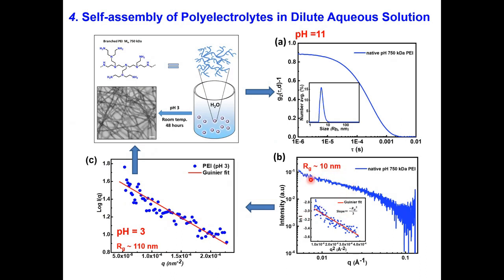And if you remember, I have pulled out this radius of gyration using Guinier analysis. That is, I take a certain region of this particular scattering curve and fit it to this equation, find out the slope and get the value of Rg. So the Rg gives me a value of 10 nanometers. This is for this particular chain only. But if I bring this system to pH 3, now you start seeing these fibrils, and the mechanism of this fibril formation is that these small chains aggregate to form 100 nanometer particles, and then they grow and become tubule-like structures, and then they grow further. And that can be monitored using small angle X-ray scattering.